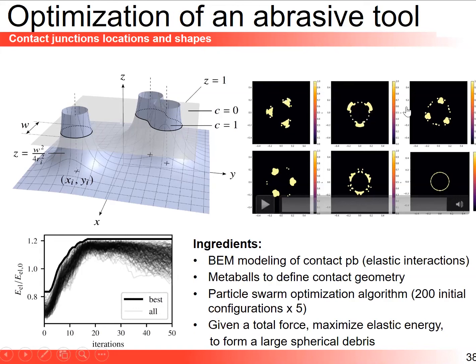and we're going to generate different initial organizations of those metaballs on our plane. You have here some yellow representation of those contact regions, and we have 200 initial configurations, and then we're going to use a particle swarm optimization algorithm to move those places around in order that, for a given total force, we maximize elastic energy, basically maximize interactions between those microcontacts to form the largest possible spherical debris. For all the simulations there is a different curve. You have 200 of those curves. We find the best solution possible. That's what you have here in this bold dark line.